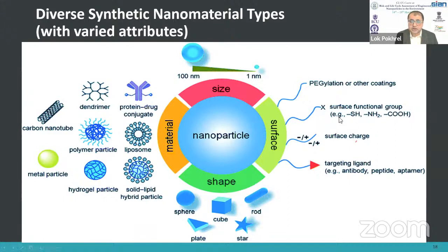So with these different types of surface capping agents, a surface coating, a surface decoration, whatever name you give it, you will generate certain types of charges, whether positive charge, negative charge, high positive, high negative, low positive, low negative, in some cases neutral charge, such as if you use PVP, polyvinyl pyrrolidone, it tends to give very close to neutral charge. So different types of surface charges can be generated, and we can test the effect of charge on some bioassay.